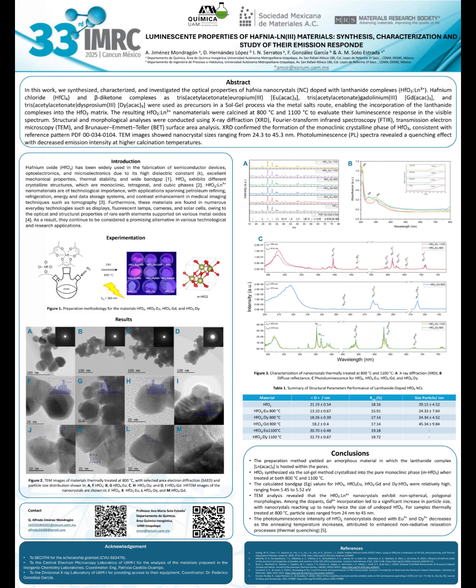Photoluminescence spectra, Figure 3c, showed characteristic emissions for each lanthanide ion. However, an important trend was observed. As the calcination temperature increased from 800 degrees C to 1100 degrees C, the luminescence intensity of Eu and Dy-doped samples decreased. This is likely due to non-radiative relaxation processes or thermal quenching, associated with oxygen vacancies or changes in the local environment of the lanthanide ions.